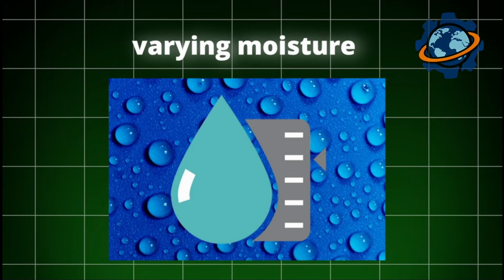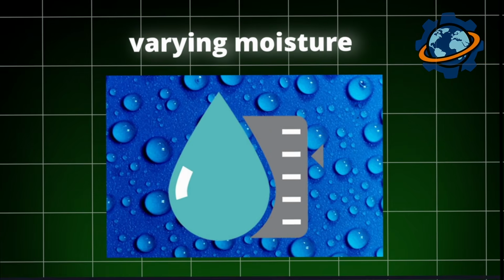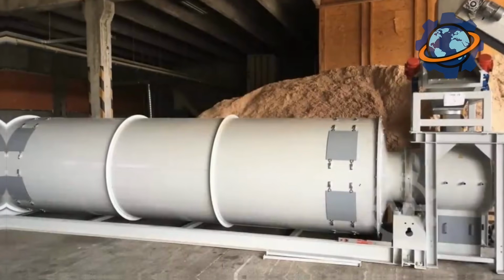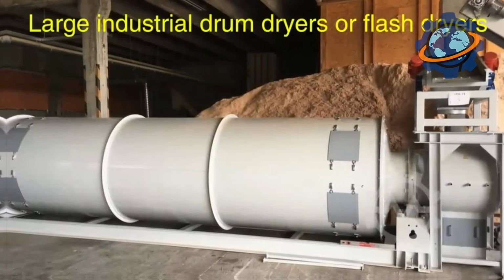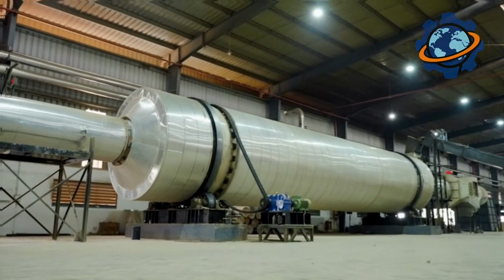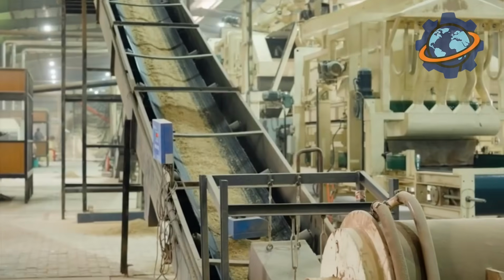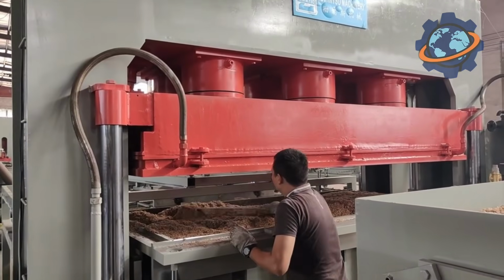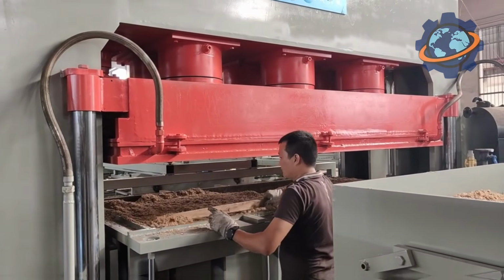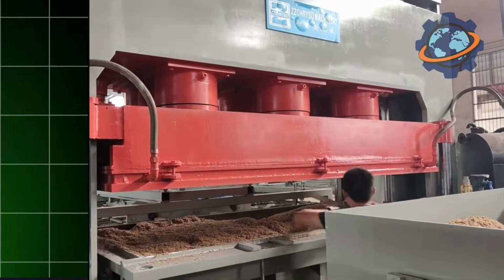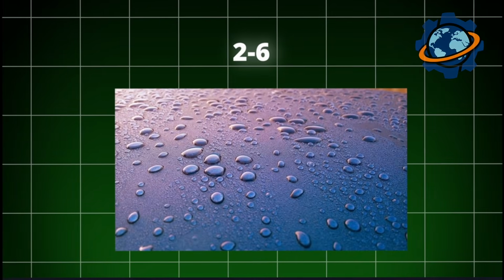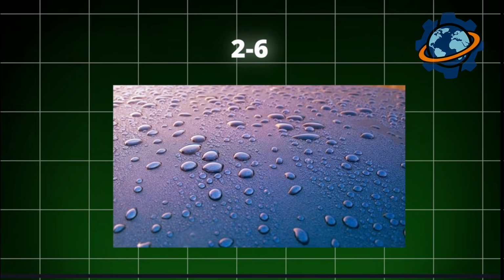The resulting chip mass has varying moisture content, which is unacceptable for quality bonding. Therefore, all the chips are sent to one of the most important stages, drying. Usually, huge drum dryers are used for this. The chips are continuously fed into a rotating drum, where they are blown with hot air or flue gases. The process is strictly controlled by automation. The final moisture content of the chips must be in a very narrow range, from 2 to 6%.